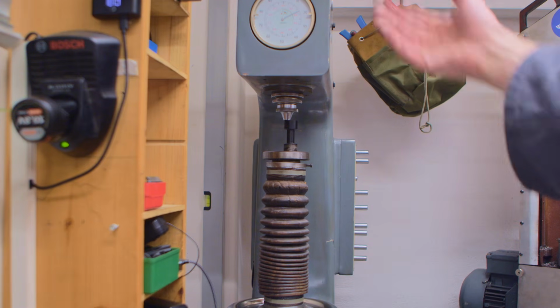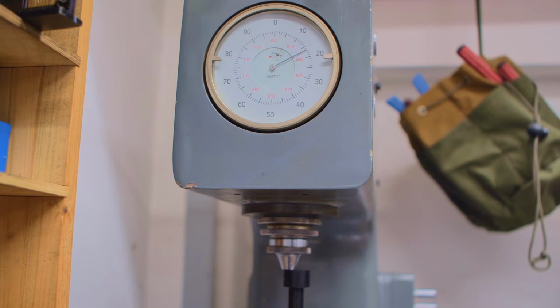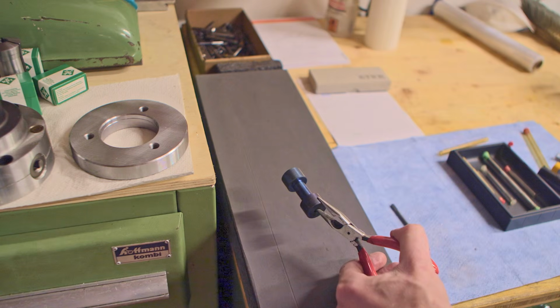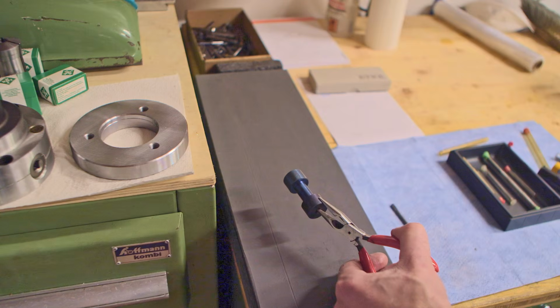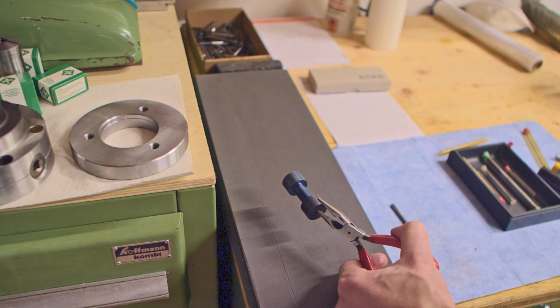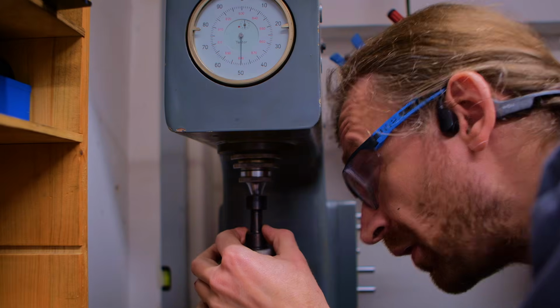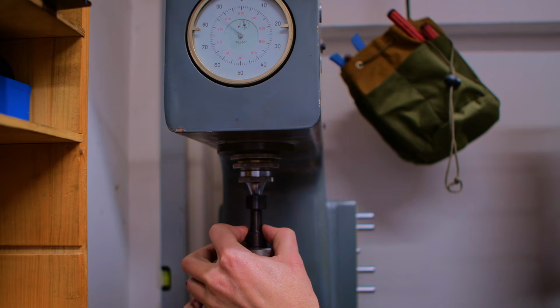Okay, it's settled out. We wait a few seconds. And when I drop the lever, we will get our real hardness reading. Yeah, that's 63 Rockwell C. That's about as hard as O2 will get. Had it in the oven for 1 hour at 350 degrees Celsius. This should give us 54 Rockwell C. Okay, let's check hardness after tempering.